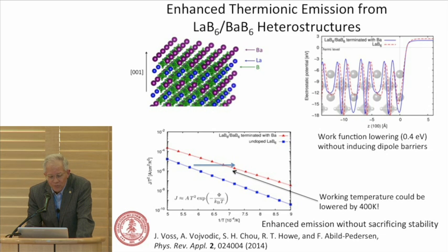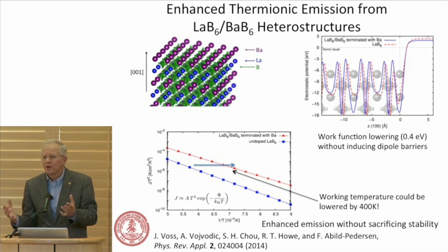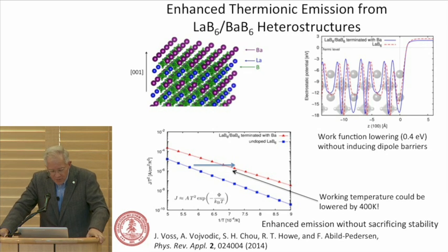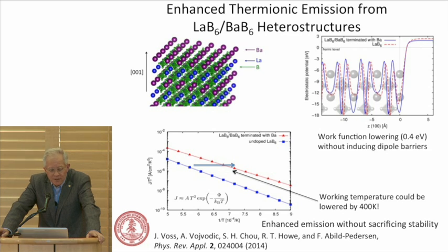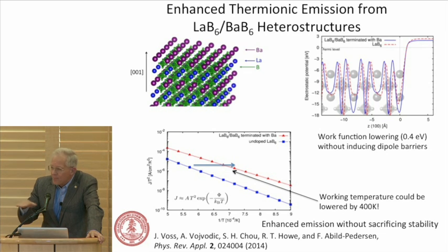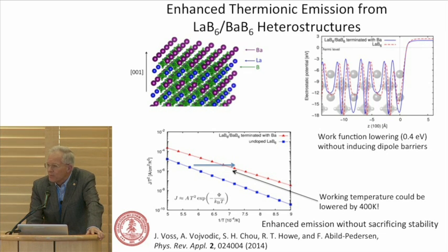Lastly, another paper with Johannes looked at lanthanum hexaboride, which is a standard cathode material, with a layer of barium hexaboride. You're able to lower the work function by 400 millivolts without any dipole barrier. So one challenge in talking it over with, can we go synthesize this? That has proven to be challenging. What would amount to an epitaxy of a monolayer is currently beyond our technology. But this would point in a new direction for getting materials that are fundamentally higher performance, maybe lowering the working temperatures substantially.